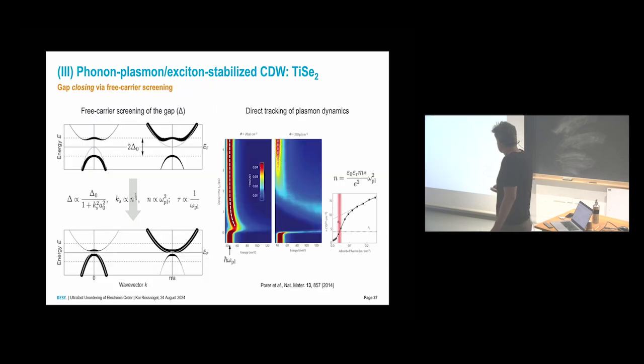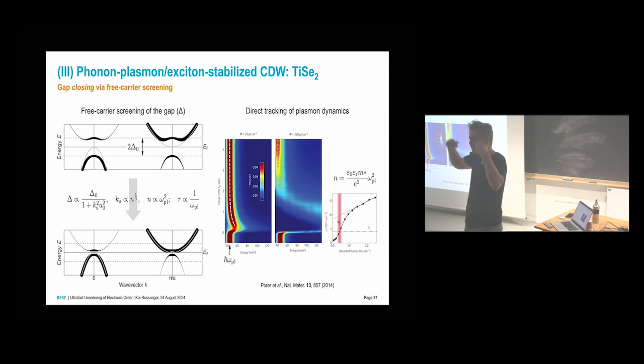you see it directly, the free carrier plasmon really has low energy, because the charge carrier density is low from the beginning. You start out with a near semiconducting picture because you have only a small band overlap or a small gap. Whereas in the more conventional charge density wave systems, they are more metallic, and the charge density is much higher, and you do not change much.